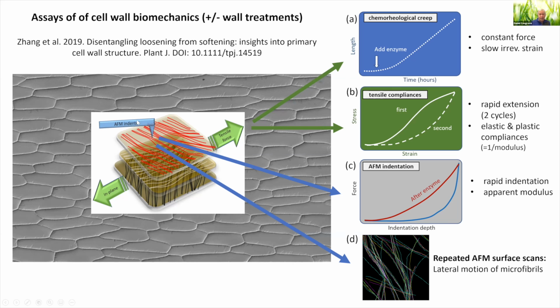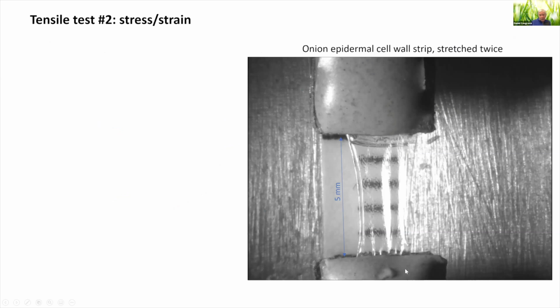We can indent the cell wall with the AFM, so poking a needle from the side, and get some mechanical properties at right angles to the tensile or in-plane direction of the cell wall. And then with the AFM, we can see how the microfibrils move as we subject them to a dragging force. So we can measure the lateral motion of microfibrils. I'll just show you one movie of this mechanical assay.